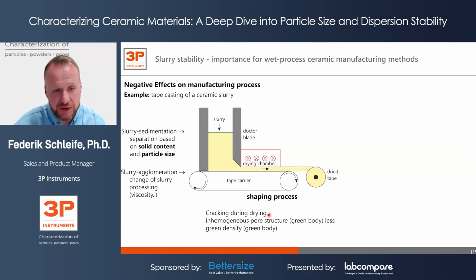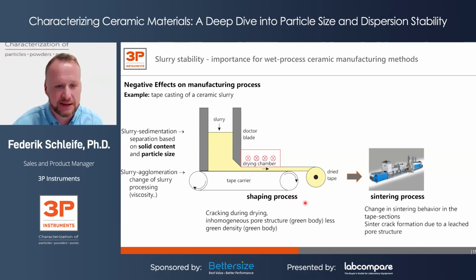Furthermore, during the drying process, an inhomogeneous pore structure in the green body will lead to cracking, and in the end to a smaller green density. Therefore, in the sintering process, if this is heterogeneously formed, you might find a change in the sintering behavior from different tape sections and some sinter crack formation due to the pore structure not being as you desired it.